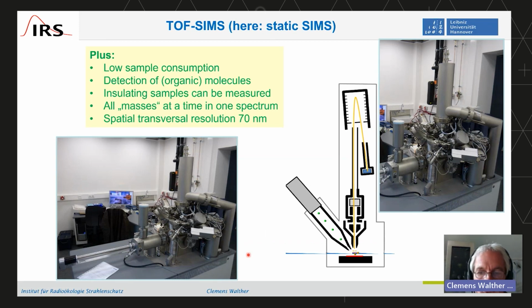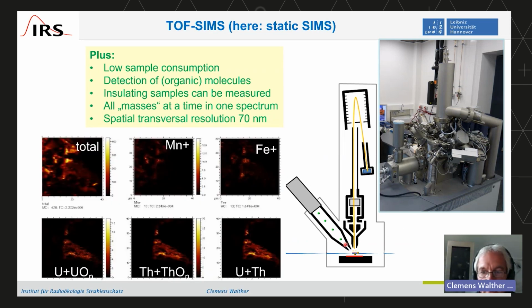A typical workhorse for nuclear forensics is secondary ion mass spectrometry, because you have a low sample consumption, and in the case of so-called static secondary ion mass spectrometry, you can also measure insulating samples. That is interesting in environmental monitoring, where samples found in nature typically are not conducting, and you end up with a rather good spatial resolution. The idea is that primary ions hit a target. Hitting the target gives rise to emission of neutral atoms and ions, and the ions are extracted into a time-of-flight mass spectrometer. You will see an animation just later on. Then they are selected by mass over charge ratio, and you get information on the mass of your samples.